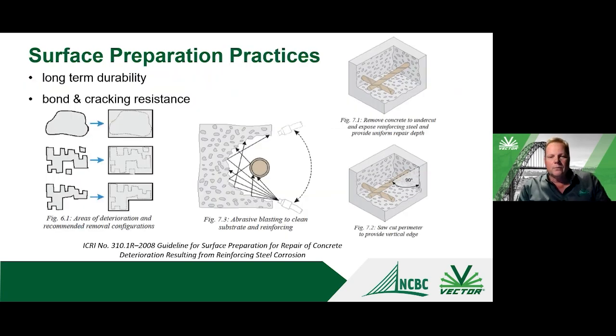So once again, these are images from the ICRI guideline for the surface preparation. So, just following some good techniques. If you look at the images here on the left, if you did a sounding or delamination survey, you may end up seeing that your spalled or delaminated areas follow the reinforcing steel and may have a pattern. I'm looking at the second one here, for example.